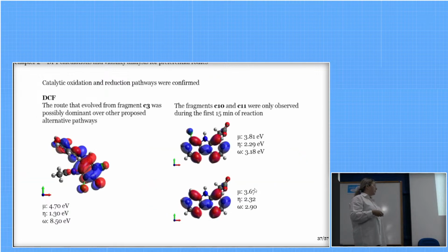And for diclofenac, the route that evolved from fragment C3 was possibly dominant over the other proposed pathways, because here we see a very high increase in electrophilicity for this molecule, much higher than for any other compound reported. And as hydroxyl radical is formed, it would preferentially interact with this compound, leading to faster mineralization. And the formation of fragments C10 and C11, which were the reductive fragments, was observed only during the first minutes of reaction. So, as these fragments were no longer formed, the reaction speed increased.